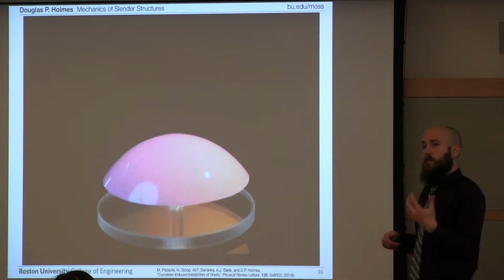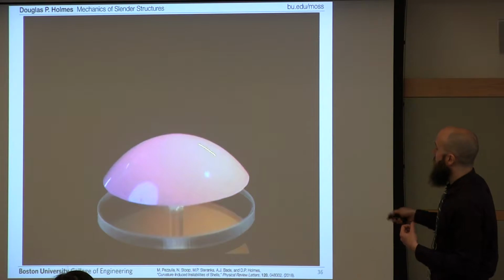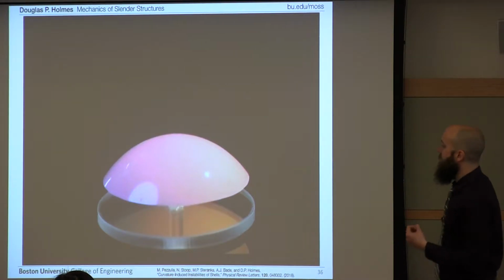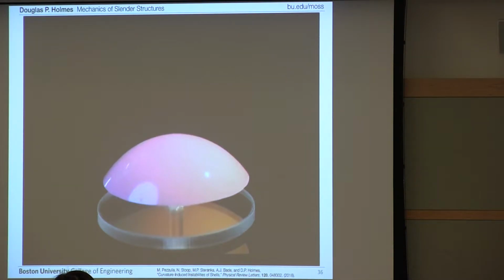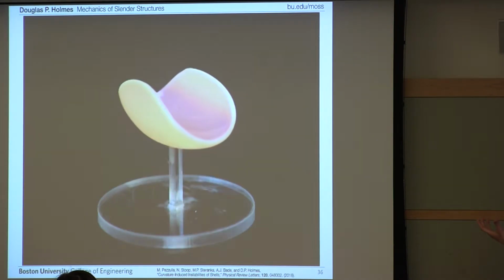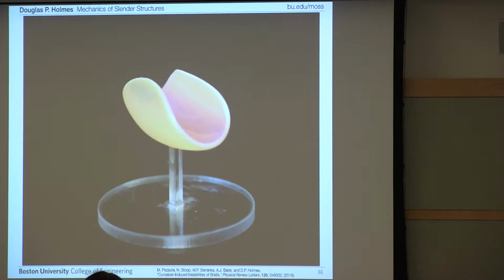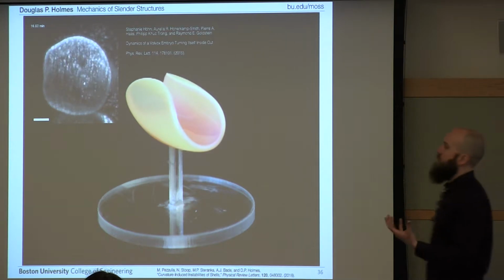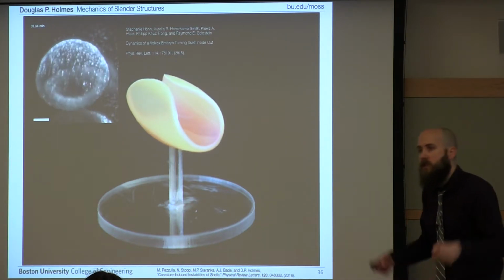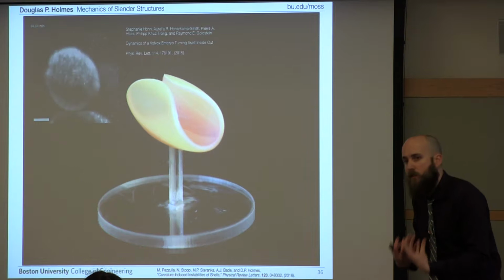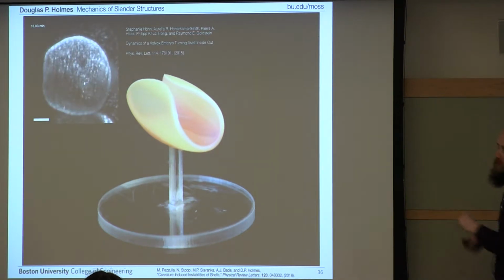If you switch the stimulus and you put the shrinking part on the outside and the growing part on the inside, you switch the instability. You completely change the instability. As we let natural curvature swell this structure, what you find, if you wait long enough, is that your structure snaps. This kind of looks just like that Volvox video I showed you before, in which you have natural curvature acting on a shell, you get to a certain critical point, and this thing completely flips itself inside out.